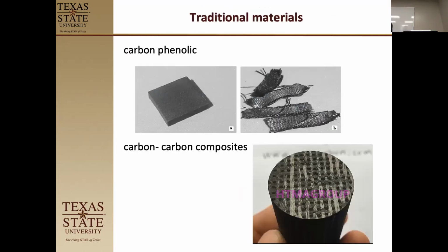So the classical one is just your carbon phenolic. So it's a phenolic resin. I'll show you the structure later. Using carbon fibers, and you can do different orientation patterns. I've seen a really cool one where they started with a crisscross pattern, but then they did an on-edge pattern right at the nose cusp. So it was ablating on the front surfaces of the fibers. Then the carbon-carbon composites typically are phenolic composites that have been sintered so that most of the organic is baked out of it. So you have a carbon matrix binding the carbon fibers.